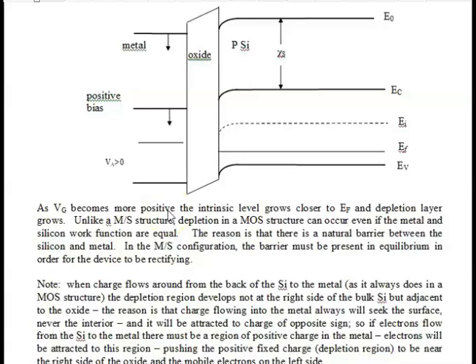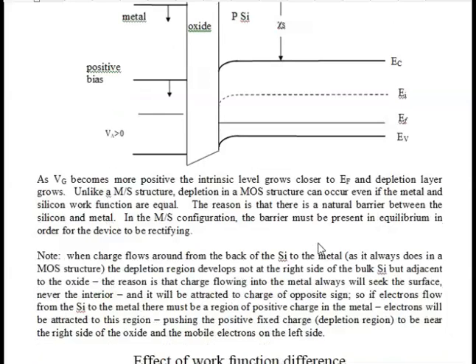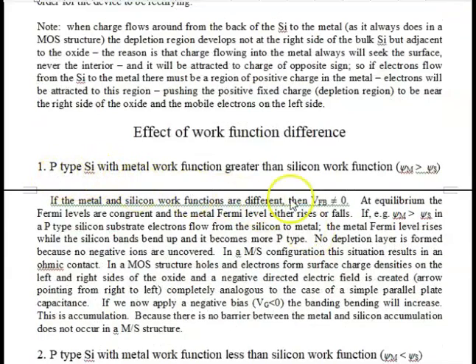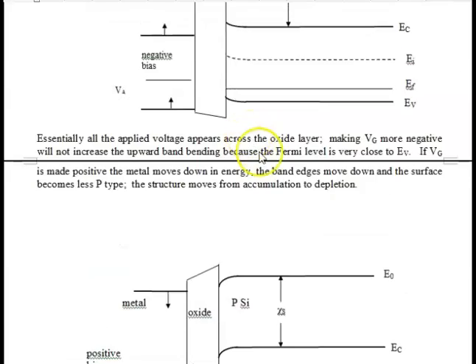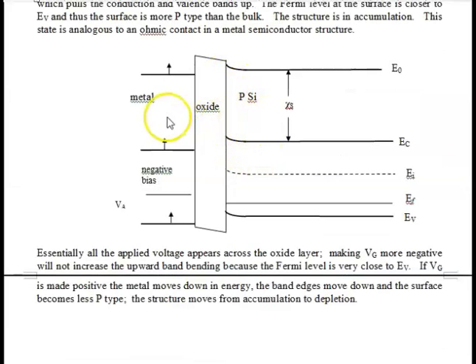So now we look at the situation of the structure where the metal work function and the silicon work function are not equal. The first thing we have to realize is when we have a difference in work functions between the metal and the silicon, the flat band voltage is not equal to 0, and in equilibrium we're going to be either in accumulation or in depletion. So let's start with the non-ideal case for P silicon, where the metal work function is greater than the silicon work function. In that case, we're going to be in accumulation at equilibrium. The P-type silicon surface becomes more P-type than the bulk, and we have positive charge here at the oxide silicon surface and negative charge on the metal surface at equilibrium.